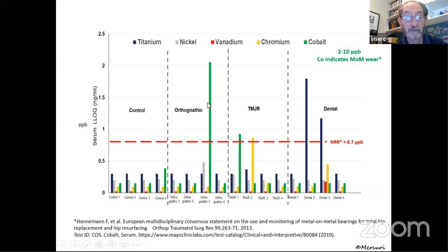So here's our controls. Here's our orthognathic patients. And as you would expect, since most of our orthognathic materials that we use for fixation are titanium, the titanium level, which is the blue here, would be the highest. This patient, we don't quite understand why she had so much cobalt in hers. We're still trying to figure that one out. So she was the outlier. But with temporomandibular joint replacement, you can see the chrome and cobalt ions went above the normal reactive range of 0.7 parts per billion.